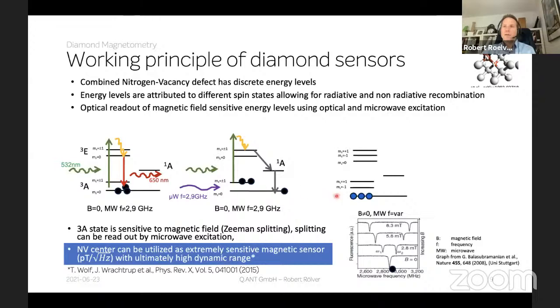And then if you apply an additional magnetic field other than 0, then you have this level splitting, and you have two positions in the microwave spectrum here where the light goes off. And the energy splitting, frequency splitting, is proportional to the magnetic field. So what you see here is the ingredients you need: the diamond, then the light excitation, the microwave field, photodetector in the end, and of course then additional ingredients shown on the next slide.